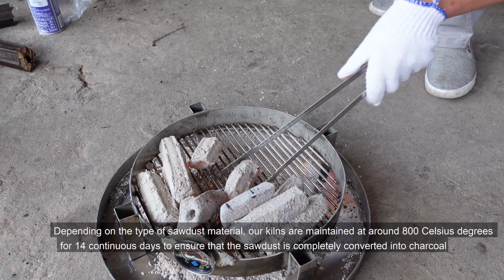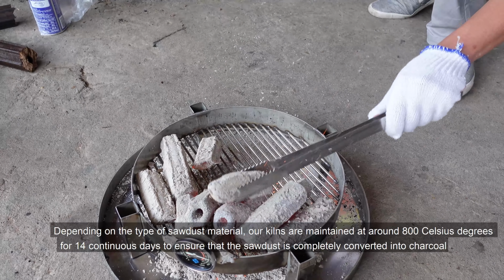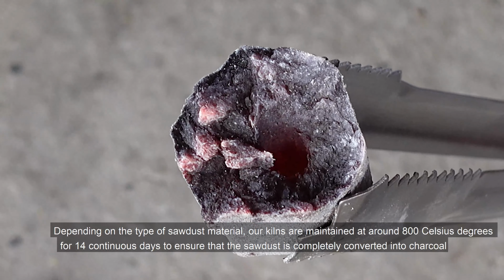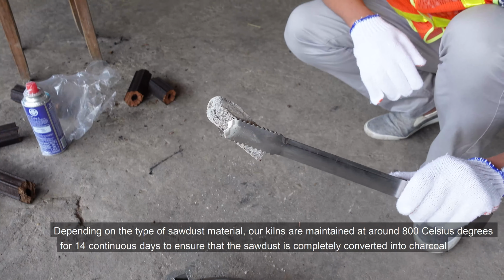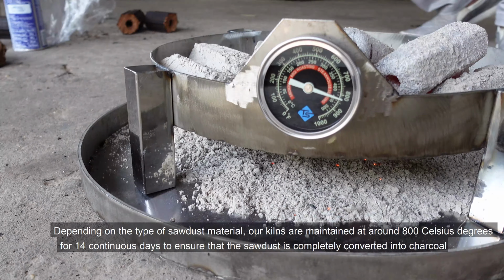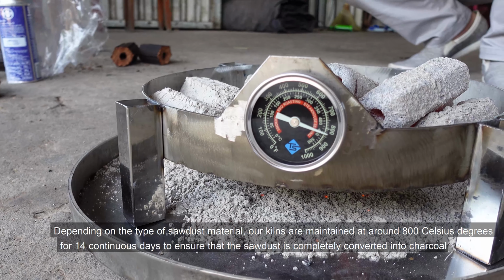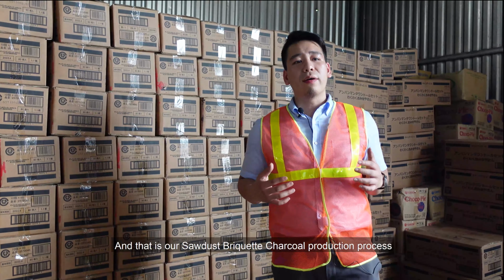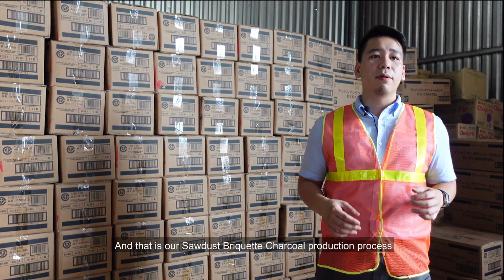Depending on the type of sawdust material, our kilns are maintained at around 800 degrees Celsius for 14 continuous days to ensure that the sawdust is completely converted into charcoal. And that's our sawdust briquette charcoal production process.